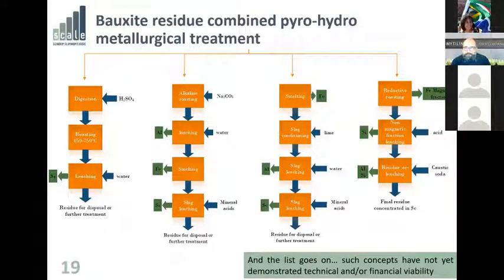So instead of smelting, you can try to do solid state reduction and try to extract a magnetic fraction and then leach out the non-magnetic fraction first with acid to get silica and then with caustic soda to get aluminates. And eventually have a residue with scandium in there. So definitely this list is not exhaustive. There's definitely more flow sheets out there.